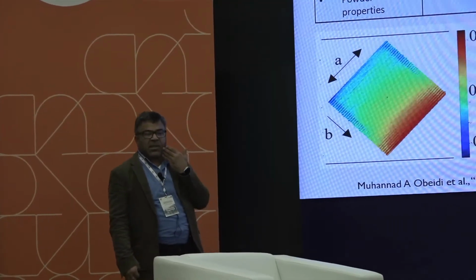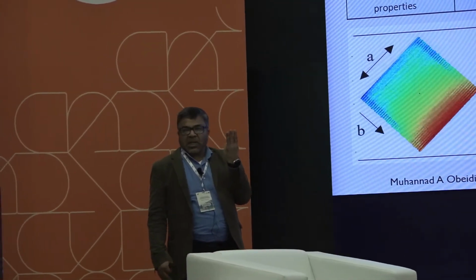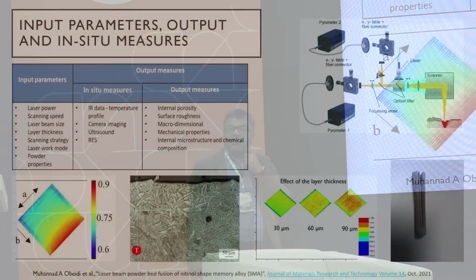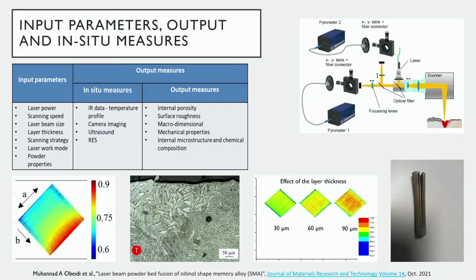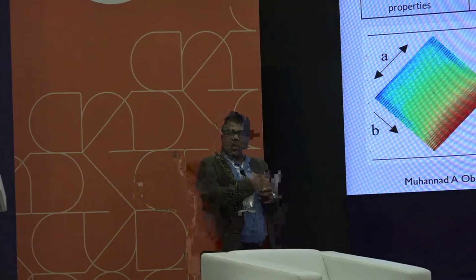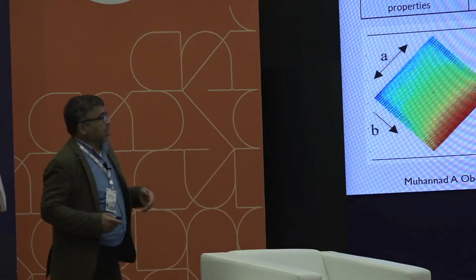So, for example, in dentistry, we have 3 levels of different surface roughnesses in one implant. For the bone growth and gripping, we will be looking in the range of 20 microns. Above that, for the protein growth, we'll be looking into 5 microns. So the best solution is to post-process the part after printing, polish it, and then re-roughen it, which is called texturing. So I apply the texture that I need.